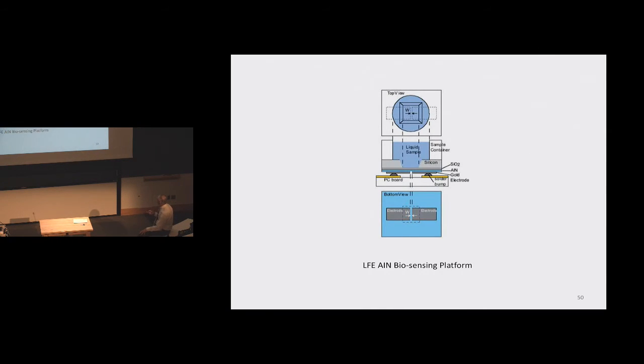The aluminum nitride or zinc oxide configuration, this represents the liquid sample. This is carved out of silicon. This is an SiO2 layer that's used to add temperature compensation. There's the tiny aluminum nitride. There's the 2 gold things, and there's the PC board that holds it up. This is the top view, and this is the bottom view.